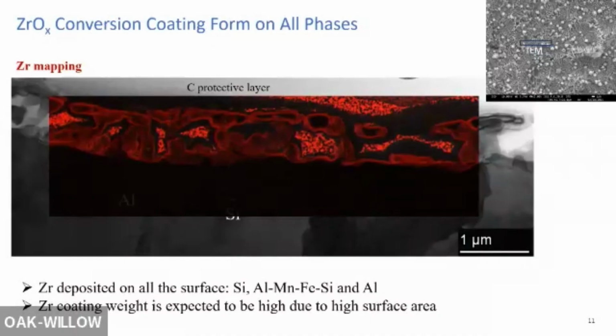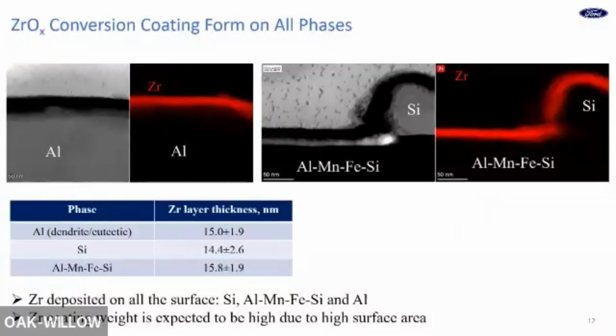Now we know zirconium can form on the surface, but we know in the bulk structure there are three phases, so we take a further look at each phase to see any difference in the zirconium deposition. First on the aluminum phase, this is aluminum, and this is the zirconium. They're pretty uniform. And this is the silicon phase. This is the manganese iron silicon particle phase. Also, it's pretty uniform. Actually, we measured the zirconium thickness on each phase at different locations. The layer is similar, around 15 nanometers.